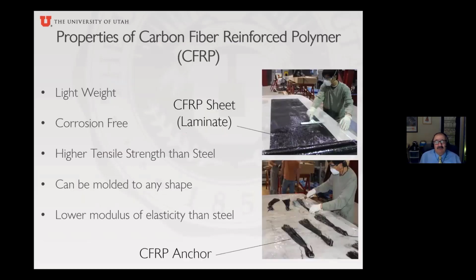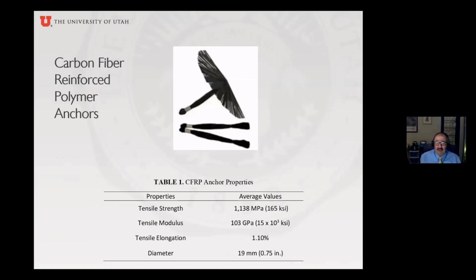So just a little introduction for those of you who are not familiar. Carbon fiber reinforced polymer is lightweight, is corrosion free, has a higher tensile strength than steel. It can be molded to any shape, but it does have a lower modulus of elasticity than steel. So in this work, we actually used quite a few different types of materials. We used a carbon fiber sheet, as you can see here, which is a laminate. Then we used carbon fiber anchors, and we used these in a couple of ways, as I will show later. It looks like a braided thing, and that's what it is, but it's very strong. You can see here the tensile strength is 165 ksi, tensile modulus 15,000 ksi. But of course, the downside is tensile elongation is only 1.1%. And the anchors we used were 3/4 inch diameter.